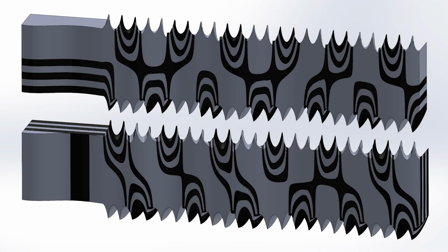This is consistent with the idea of saving precious metal, which was important in the time when the original blade was made. Another detail that I learned about the checkers is that for this pattern, it is okay to mess up the orientation of the bar prior to grinding. I did not need a pilot punch hole in the bars, as you arrive to the same pattern in the center of the bar, whether you grind from the top or from the front of the bar. One more thing. Since we are grinding to the center of the bar, it does not matter if we twist these bars clockwise or counterclockwise. In other words, despite the difficulty with this pattern existing only at a very narrow margin around the center of the bar, it is a very forgiving pattern in terms of orientation of the bar itself.